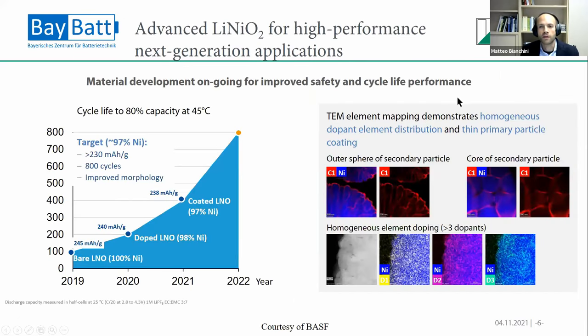And I have only one slide really discussing one real material because it's something that's close to my heart because I worked on it in the Bella Lab in Karlsruhe in the last 3 years, and it's also a focus of great attention in BASF. So this is lithium nickel oxide. And that's because, I mean, this is a material that was known in the 90s already. It would be a dream material, but it has too low stability. So it's not really stable enough thermally, electrochemically.